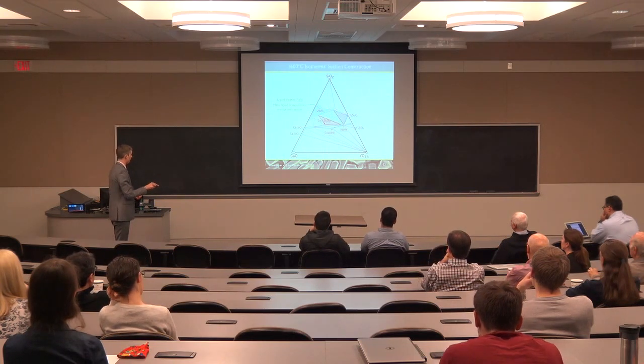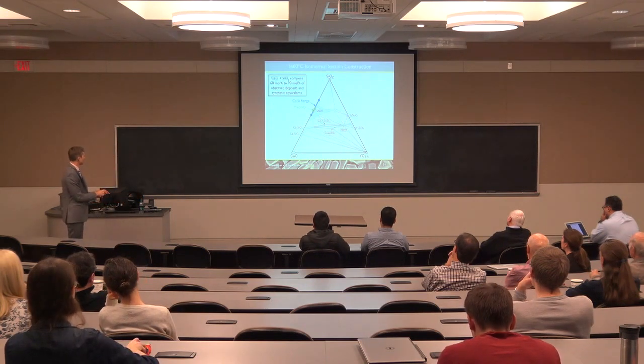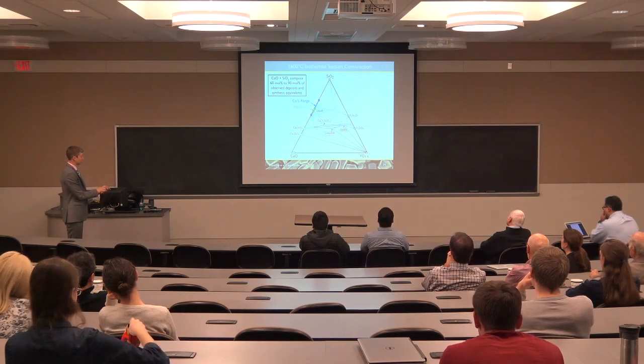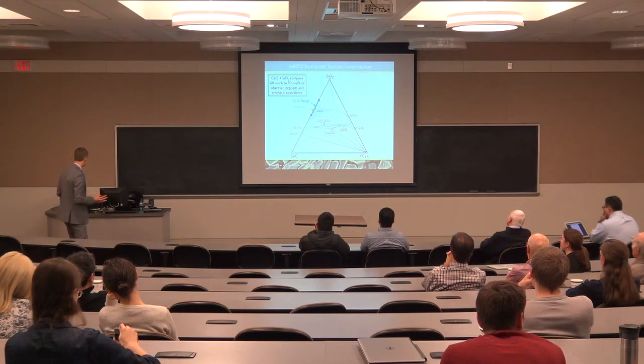So this sort of a liquid. We've got a liquid somewhere here. Many of those liquids, as yttrium dissolves, will form apatite. But we also have these fields on both sides, and so the bounding cases would be if we have a really silica-rich liquid, we might crystallize out this silicate, or if we have a calcium-rich liquid, we might crystallize out this silicate. And this is sort of the range of calcium-silica ratios in the typical deposits that are observed in engines.